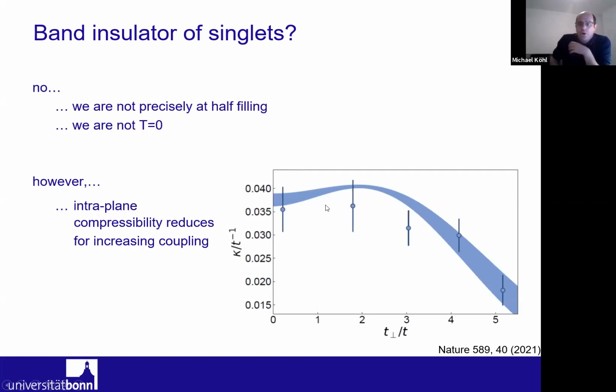But if we go on and increase the coupling between the planes, we actually see that the compressibility goes down. And we believe that this is a first hint that this singlet state, or this area of the singlets, indeed is more insulating than the standard two-dimensional Hubbard plane is.